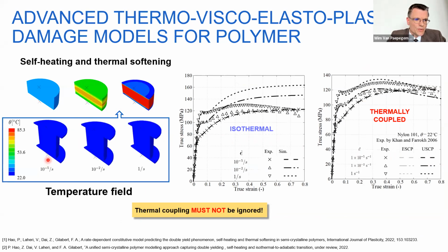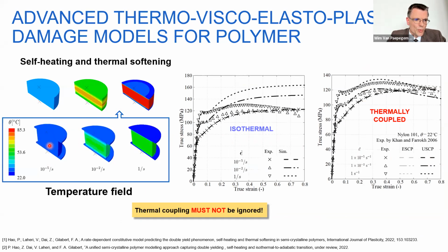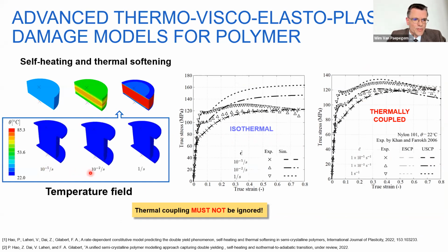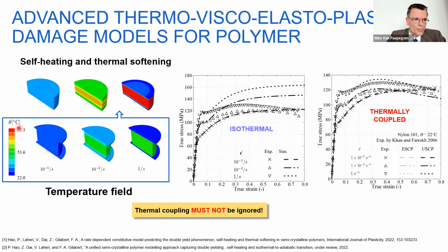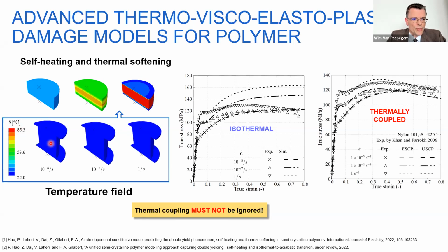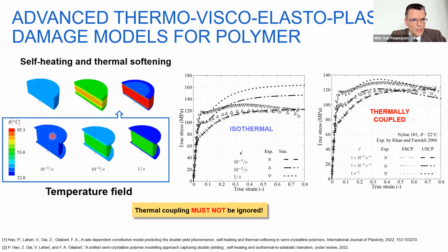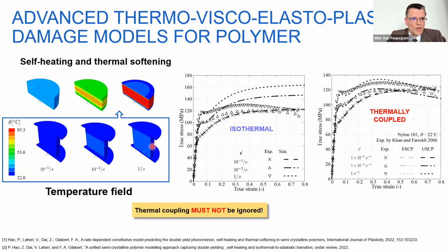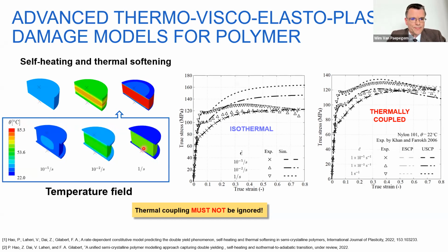So if you see here, in this case, it's a compressive test on a pure polymer disk at very slow rate, at higher strain rate, and at very high strain rate. And this is the temperature which is plotted. And at slow strain rate, the temperature increase due to plastic deformation can just dissipate to the steel platens of your machine. But when you have a very fast loading, the temperature stays contained.